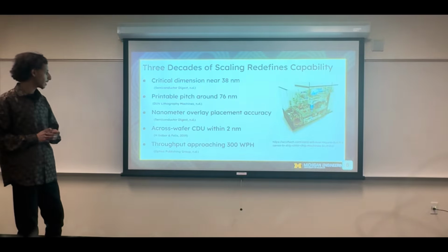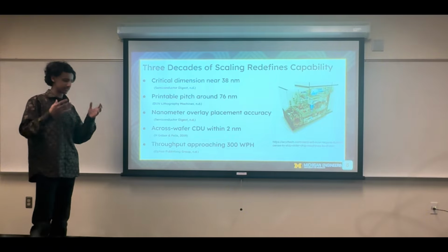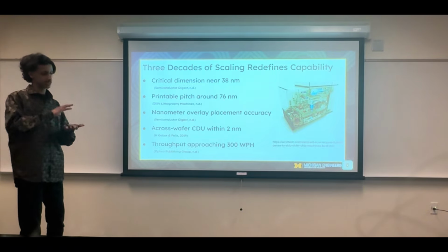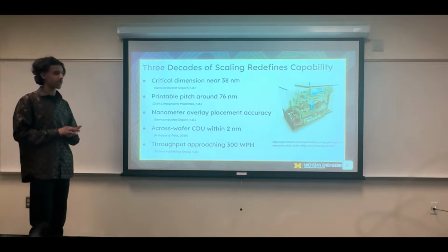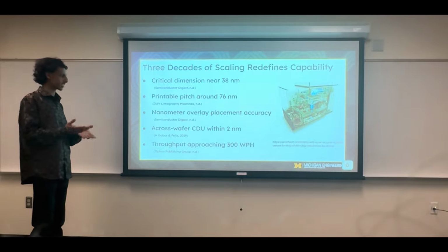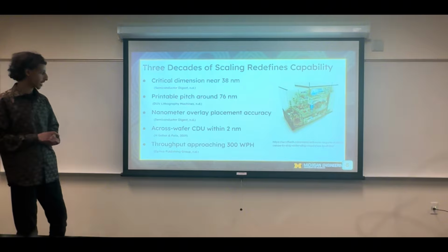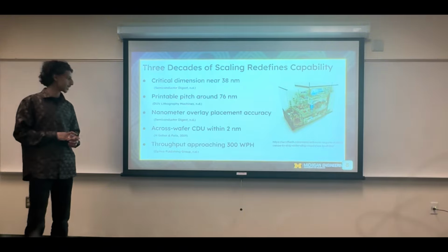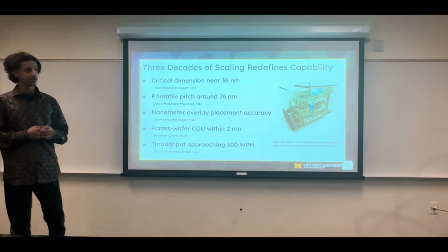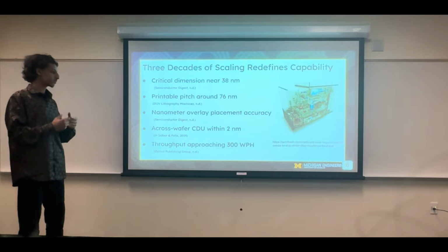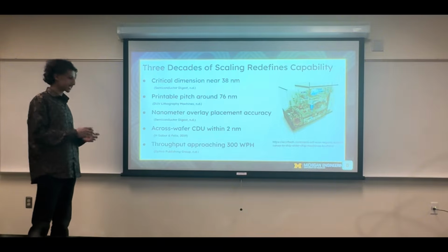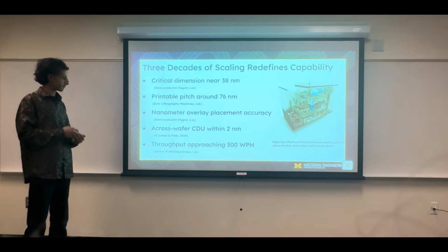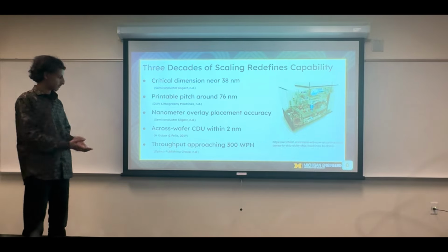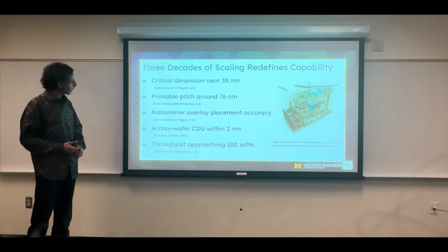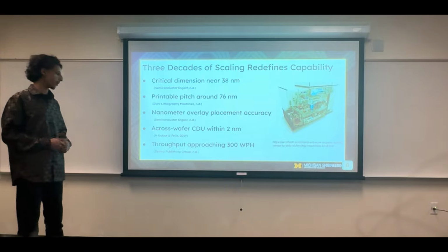The printable pitch size is around 76 nanometers, and a pitch is essentially the center to center distance between two feature sizes. And the overlay accuracy is how accurate a lithography machine is able to place a layer on top of another, and it must be within 1 nanometer for the wafer and the chip itself to function and produce a much higher yield rate. The critical dimension uniformity is essentially how consistent each feature is throughout the wafer and the chip itself. So with a much lower critical dimension uniformity, it produces a much higher yield rate. And as mentioned before, DUV lithography, while maintaining all these metrics, must produce 300 wafers per hour.